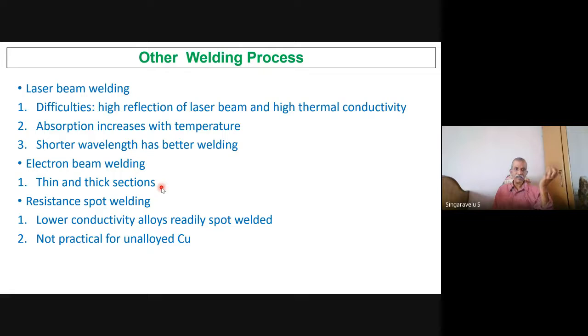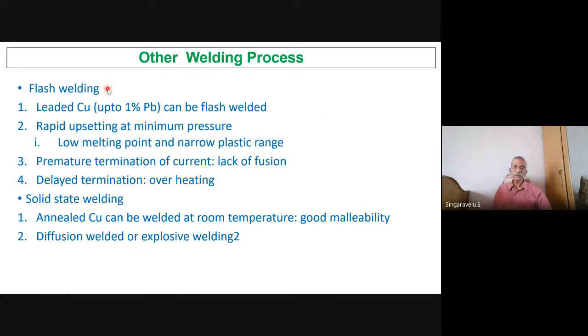Electron beam welding, both thin and thick sections can be done. We can do resistance spot welding. Lower conductivity alloys can be easily spot welded. Not practical for unalloyed copper. Right? Flash welding we can do. Leaded copper, up to 1% lead, can be flash butt welded. Rapid upsetting at minimum pressure.